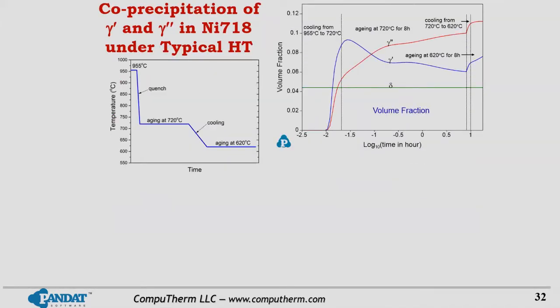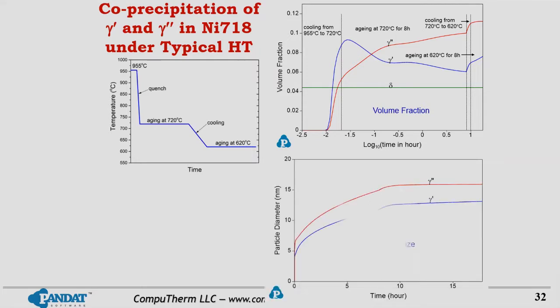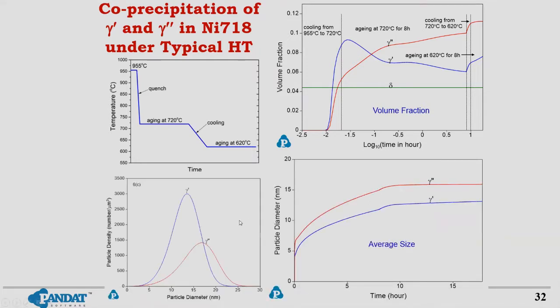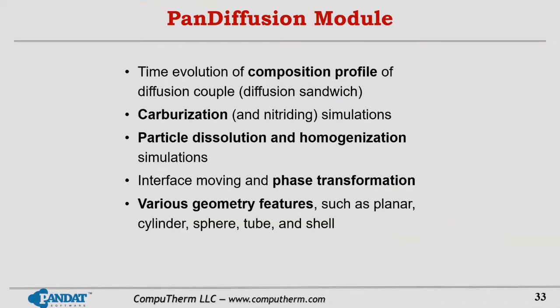This is an example of gamma prime and gamma double prime co-precipitates in a nickel-based superalloy. This is a typical heat treatment condition, and we can use this condition to simulate how these two precipitates compete with each other to evolve during different stages. You can see the volume fraction, the particle size evolution, and also the particle size distribution.